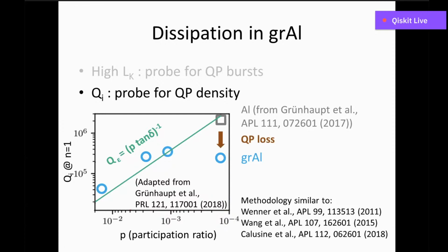We attribute this to quasiparticle losses, because the kinetic inductance fraction is about an order of magnitude higher than in aluminum, meaning that we will have an order of magnitude more quasiparticles, and this can explain well this excess loss that doesn't allow us to get the same internal quality factor as aluminum. Thus, we can look at the internal quality factor of our resonators as another probe to check the quasiparticle density.